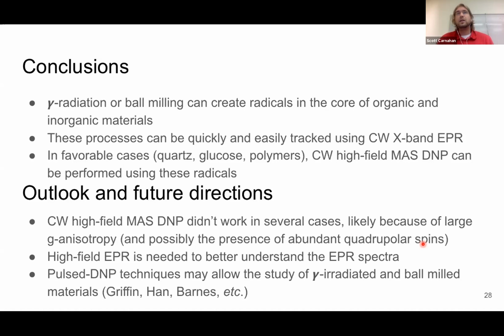High field EPR would be really effective in helping us understand the radicals, because I'm doing X-band EPR, which is 9 gigahertz, and then I'm doing DNP at 263 gigahertz, and there's a little bit lost in translation there. We have done a little bit of high field EPR, but routine use would make this go a lot easier. For a lot of these samples that didn't work, pulse DNP techniques would probably be very effective. Kong and Bob are both pioneers of this, as well as Songi Han and Alexander Barnes. If we were able to use some of these pulse DNP techniques, we could probably get some of these samples with large g anisotropies to work as well.